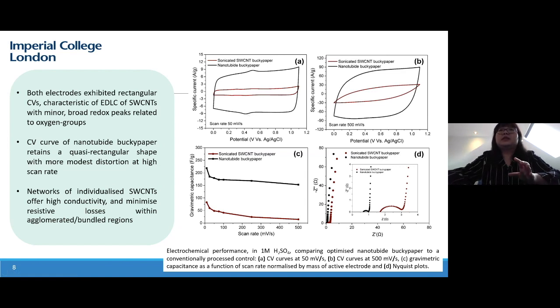However, in terms of interpreting the capacitance, the area under the CV curve shows how much capacitance you achieve. In that case, both at the higher scan rate and lower scan rate, the nanotubide buckypaper gives much better performance. And at the higher scan rate, you can see that the shape of the sonicated SWCNT buckypaper CV curve is more resistive. That also refers to the low rate capability and higher resistance in the system, which leads to a significant drop in the capacitance at the higher scan rate.